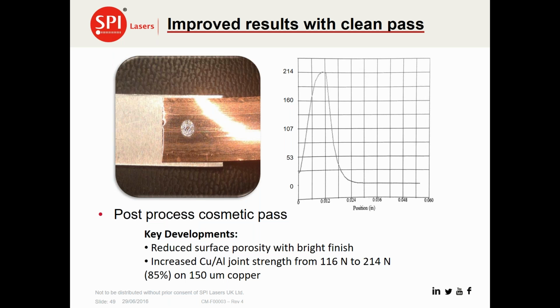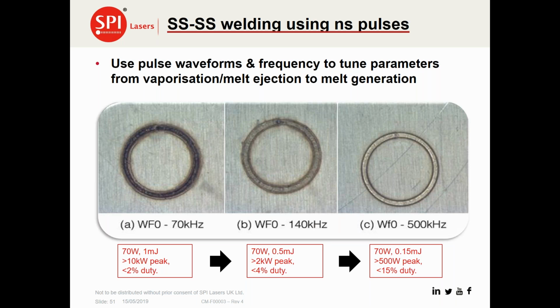So now I can take you on to some examples of the nanosecond joining process, and we'll start with some similar metal combinations. This is an example of stainless steel to stainless steel welding using the nanosecond welding process. This is actually how we first found out about this process, and indeed stumbled across it here at SPI through our applications development. It's usually believed that you need a lot more pulse energy and higher peak power, more average power in order to weld particularly thicker materials. But we actually found that for a nanosecond pulse laser, sometimes the opposite is true.